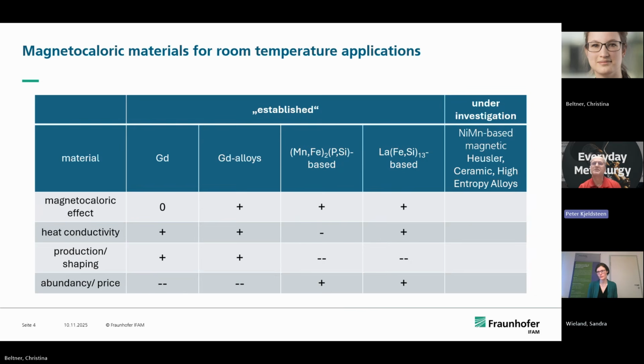I remember, I think it was the lanthanum iron silicon we used. That was adjusted slightly in the chemical composition to do that. I think this is the most used today, the lanthanum iron silicon alloy, and then you throw into this some cobalt or some manganese or some cerium and all different things to adjust the Curie temperatures. Basically, it escalates very quickly when it comes to adjusting the Curie temperature with other elements. And that makes it so challenging to find the right kind of composition and alloy to have a certain effect, and always a stable effect as well.